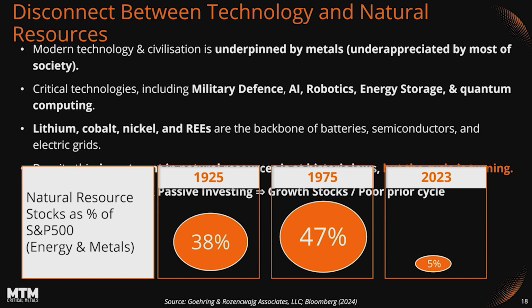And we're also looking at improving the mineral processing industry, primarily in Australia, where our headquarters is. We've had a lot of success with lithium, as Dr. Tour already mentioned. But essentially, lithium is one of the most difficult metals to extract from its mineral ore. You need a huge amount of acid and energy to get it out. As Dr. Tour mentioned, we can potentially cut out 80% of the unit operations for a typical lithium refinery using flash Joule heating under a chlorine gas atmosphere. So it's really game-changing potential for both recycling and also mineral processing improvements.